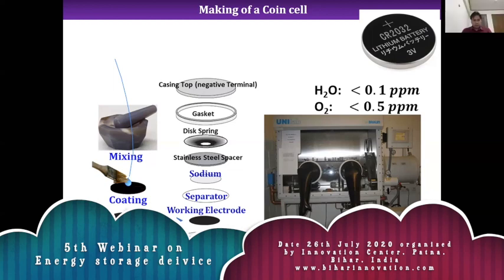And then we dry it. If the material is degrading, we dry it in vacuum. If it is not, then we can go for simple drying in a hot air oven. So this is how the material is coated.